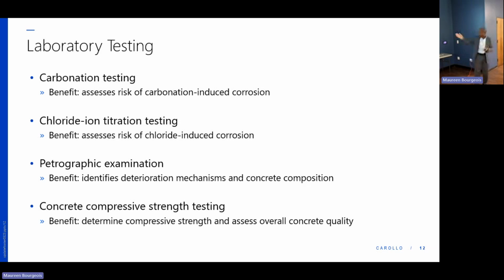And then finally, one lab test which is very important is the concrete compressive strength. Concrete is very good in compression. And that is why it acts as strong columns, because when you load it, it can take so much. But it's weak in tension. That is why you provide the steel. The load at which the concrete will fail, just before it fails, is what we call the compressive strength. So you take the core, you load it up, and right before it fails, you get that load, and that's the concrete compressive strength testing.